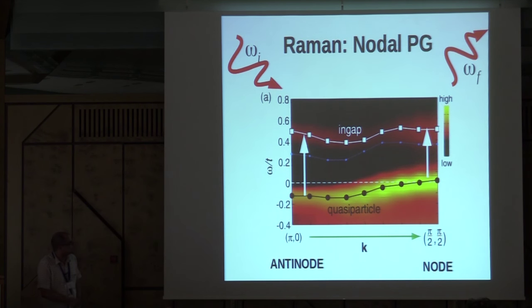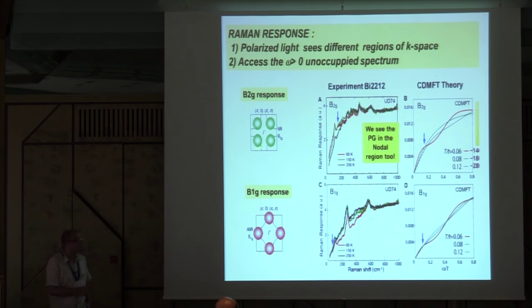Raman sends a photon into the system, so the electron will change from an initial state to a final state, and transitions of this type are possible, where the electron in the initial state is in the lower band, and in the final state, when the photon goes out, is in the other band. So we should see this band structure in Raman. Now, the problem is that we would like to distinguish between antinode and node. This is possible with Raman, which using different light polarization is actually probing different regions of the Brillouin zone. This polarization, the B2G setup, will probe more the node, the B1G, the antinode. And this is what they see.